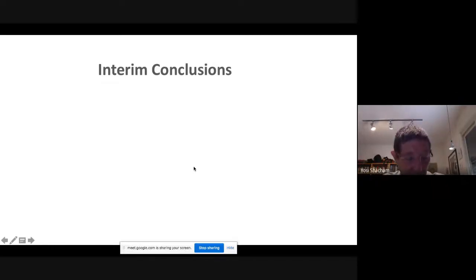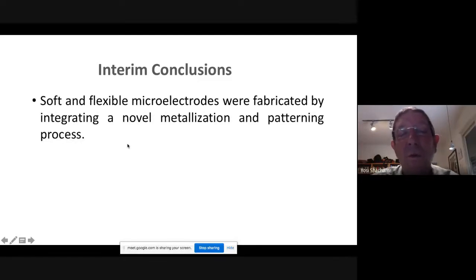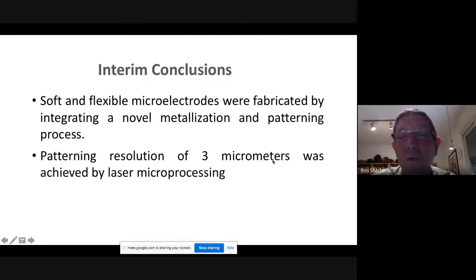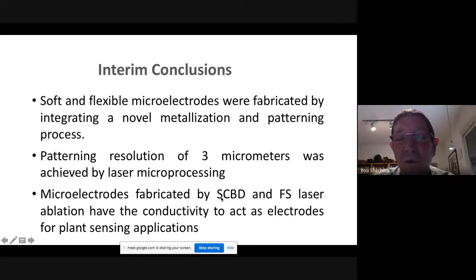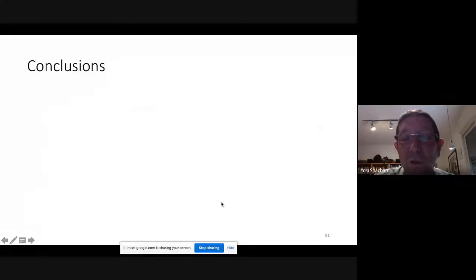So to summarize this talk, and I promised Ragini that it will be between an hour to an hour and 15 minutes, we are close to the end of this talk today. The interim conclusion about what we do is that soft and flexible microelectrodes were fabricated by integrating a novel metallization and patterning process. We can go down to 3 microns by laser microprocessing. The microelectrodes fabricated by supersonic cluster beam deposition and femtosecond laser have the conductivity to act as electrodes. We use it for plant sensing, but Professor Milani is using it for electrodes for the brain and for the skin. And there are a lot of applications for this technology now being investigated.